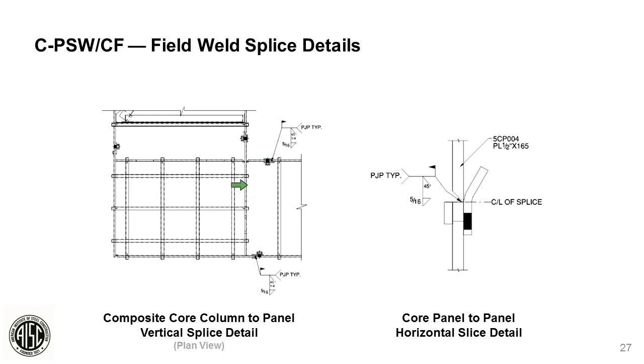So from a tolerance perspective, these two corner panels are, let's say, 40 feet apart. This panel's 35 feet long. You only had a 1/4 inch gap on each side of tolerance. So these corner columns had to be very plumb. But that root gap could be 0 on one side and 1/4 on the other, or it could, at the horizontal, be 0 at one side and vary to a 1/4, just because of tolerance.